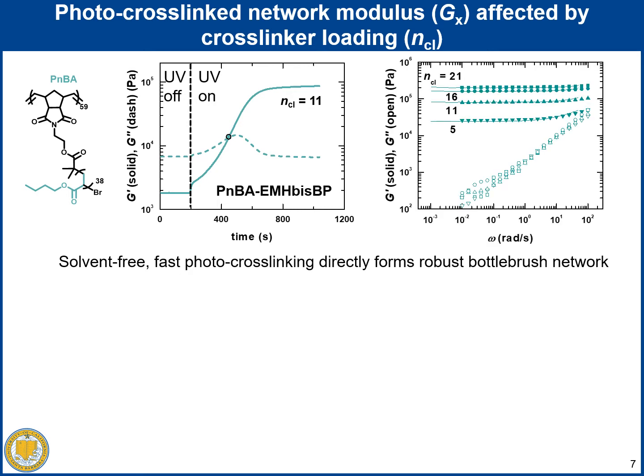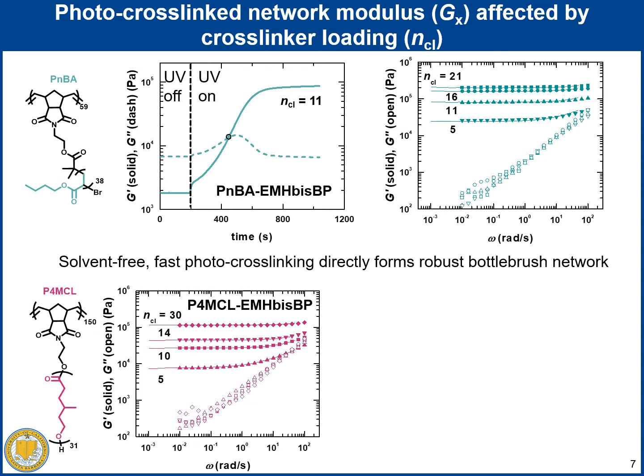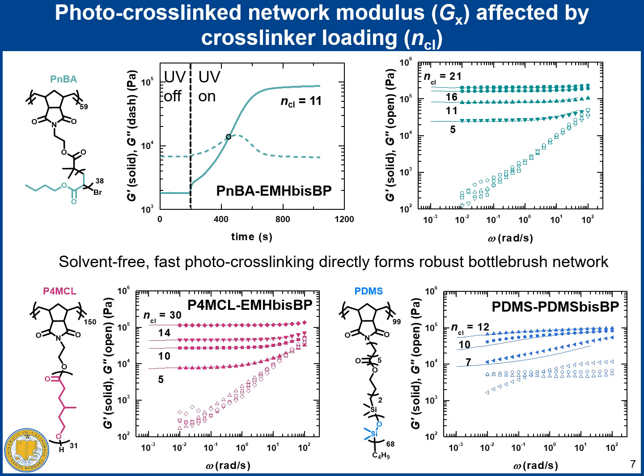Then, by adjusting the crosslinker loading, we can change the storage modulus by roughly an order of magnitude. We can again apply the same method to other pairs of crosslinker and bottlebrush polymer with different sidechain chemistry. The equilibrium network modulus, G_x, is defined in the low frequency limit, and in this case, 10 to the minus 3 radian per second.